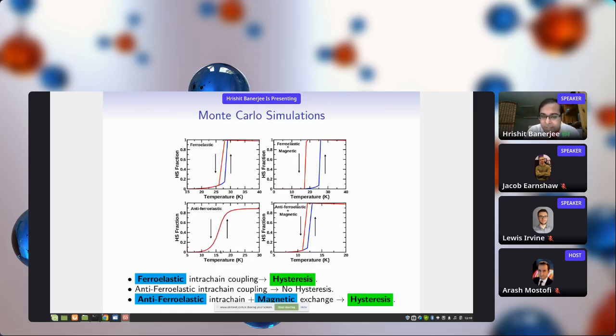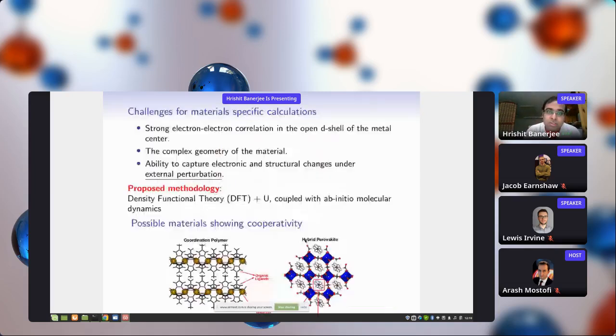So this is a weakly cooperative system, and the cooperativity increases and hysteresis pops up when you plug in the magnetic exchange. So for the antiferroelastic intrachain interaction, we have to remember that the magnetic exchange is very important to have a hysteresis effect and the memory effect.